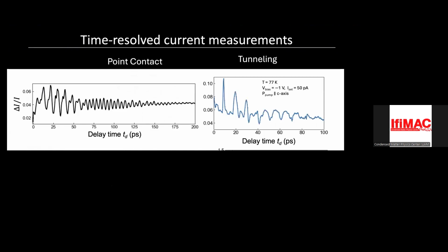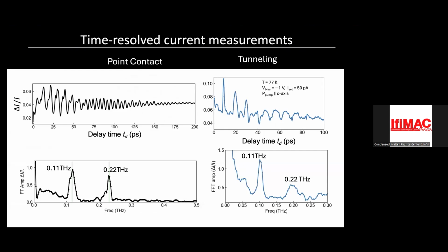And then in tunneling, we see the same thing. We see oscillations. You can take a Fourier transform of both the point contact and the tunneling. And in both of these, you see two peaks, one at 0.11 terahertz and one at 0.22 terahertz.